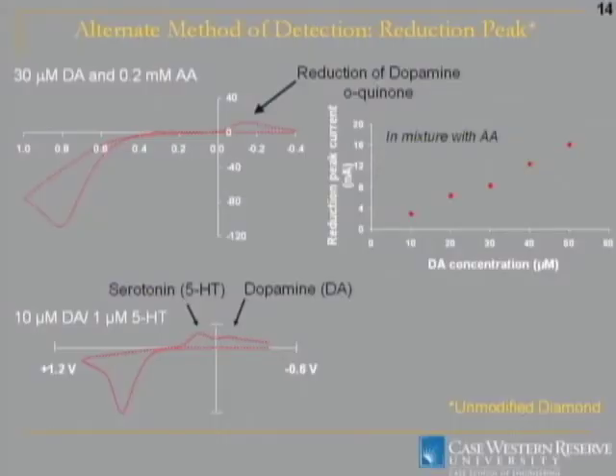This is two examples of dopamine. I'm sorry I didn't write out the words here. Dopamine and ascorbic acid, which these are in appropriate ratios of what you'd see possibly in tissue. The problem here is that ascorbic acid also oxidizes at the same potential as dopamine, and that's right here happening. And so if you're trying to detect dopamine in the presence of ascorbic acid, you're never going to be able to tell what the concentration is. But dopamine has a reduction peak, again, well defined on diamond. Ascorbic acid doesn't have one, so you can see in a mixture of ascorbic acid what the concentration of dopamine is by using the reduction peak.